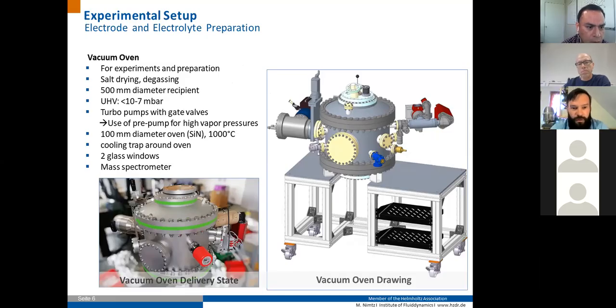A new technology to improve the salt preparation, for example, and also to improve experiments is the vacuum oven displayed here. This is a new facility which is built up and tested right now. You can see the delivery state several weeks ago here in the lower picture. This vacuum oven can produce a much purer atmosphere due to the ultra-high vacuum, 10⁻⁷ millibars, which then gives impurity levels in terms of oxygen or water, which are several magnitudes lower than the atmosphere in the glove box.